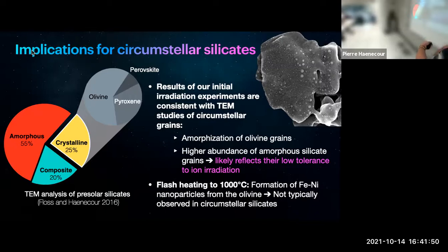We found amorphous olivine, so it's typical of what we might expect for amorphization of olivine in high energy environments. So basically, if you think about a supernova, for example, a stellar explosion, it's very energetic. It has a lot of really high energy particles. It can really easily amorphize those silicates. So it's not surprising that a lot of the silicate we have in the presolar grain collection are actually amorphous. And that's why we have a higher abundance of amorphous silicate than crystalline silicate, even in the interstellar medium.